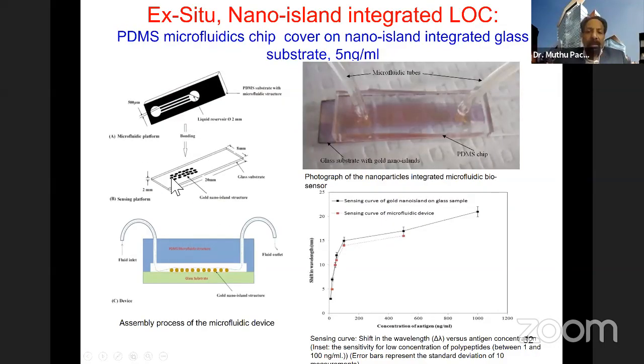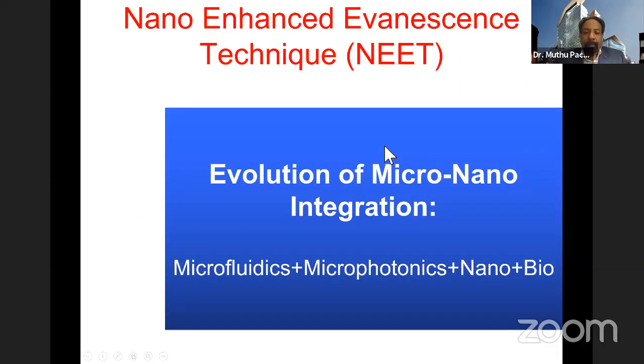So here you can see the gold nano islands on a glass substrate, and then you cover it with a PDMS microfluidic chip, and then you go for diagnosis. This is called ex situ nanosynthesis, and we got around 5 nanogram per milliliter of sensitivity in this case. So next we thought about using NEET.